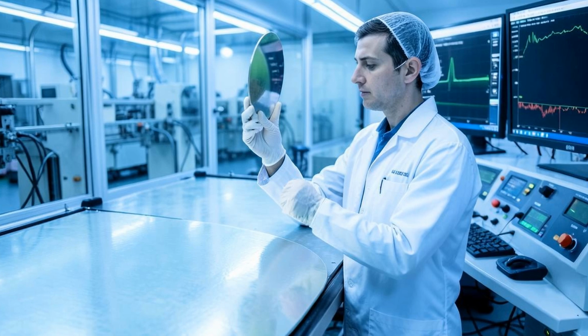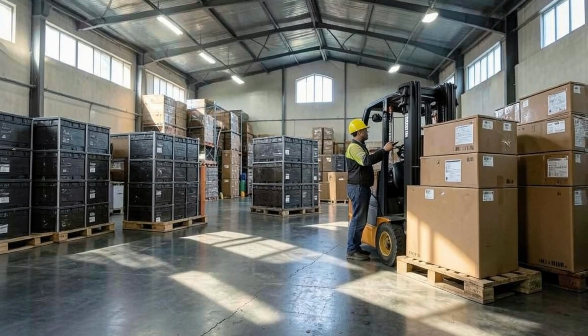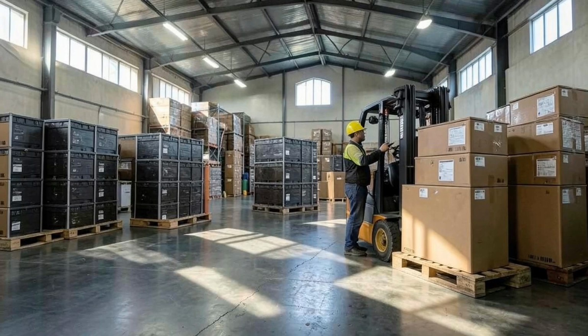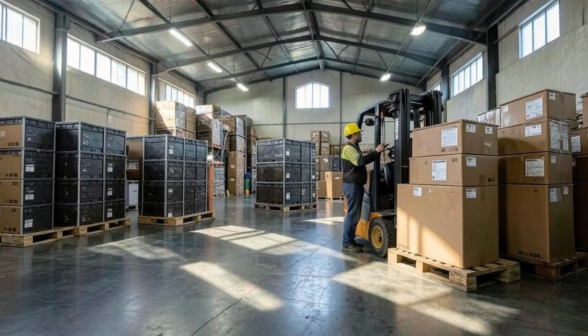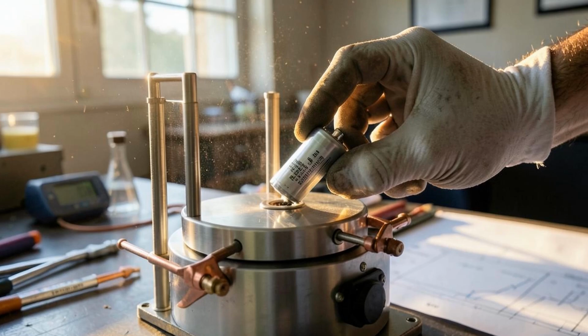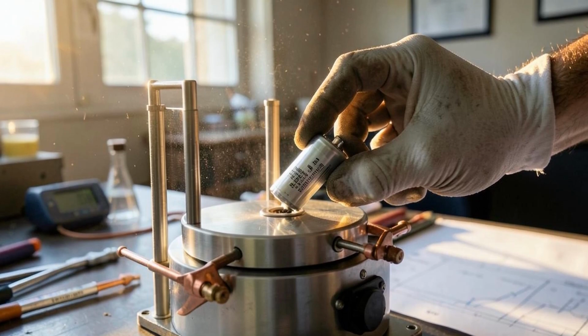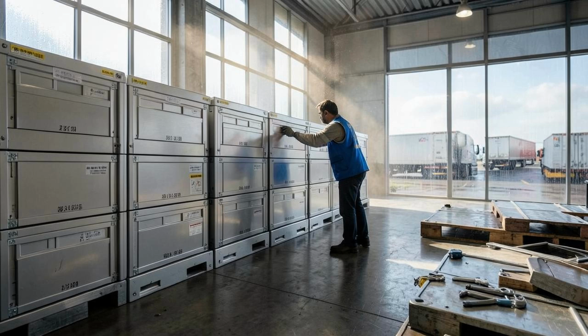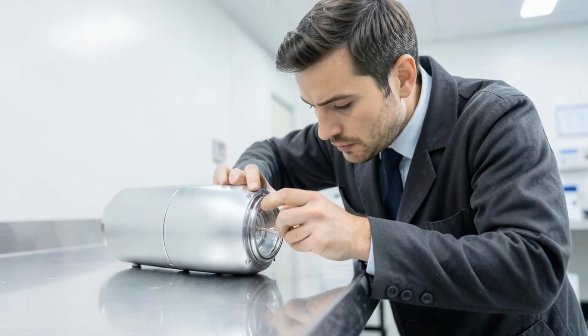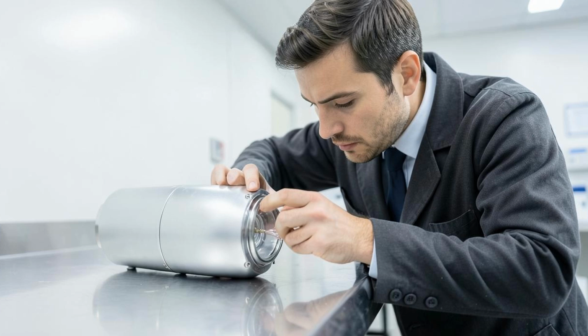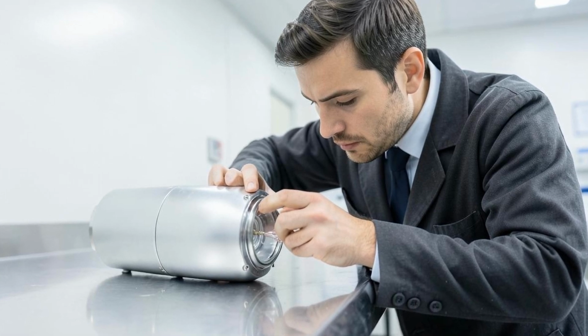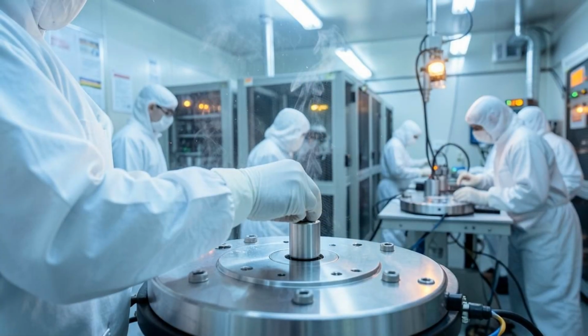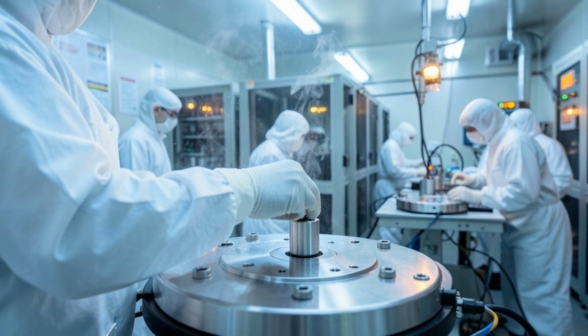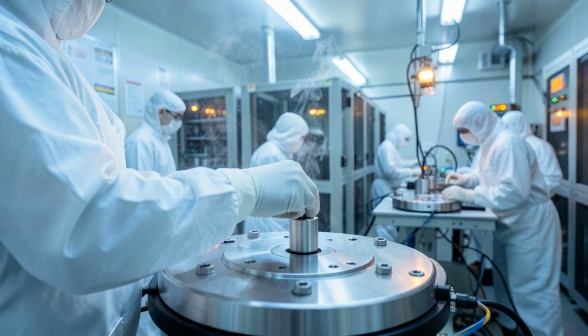The result of this structural stability is the 1,300-hour metric we started with. This number validates that the suppression of dendrite formation works effectively at room temperature. In previous magnesium systems, you often had to heat the battery up significantly to prevent corrosion or force ions through the interface. That requirement made mass manufacturing impossible for consumer devices which must operate in a wide range of ambient temperatures without external heating. By solving this interfacial degradation issue, the alloy enables reversible reactions that were previously thought too unstable for practical use. This shift from high-temperature operation to room temperature stability is what unlocks commercial viability.